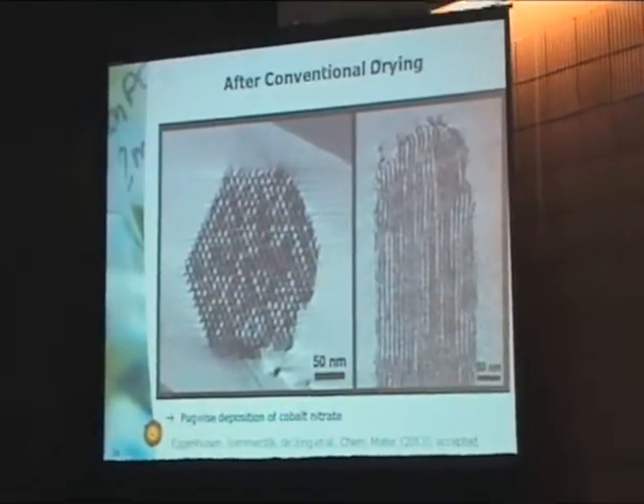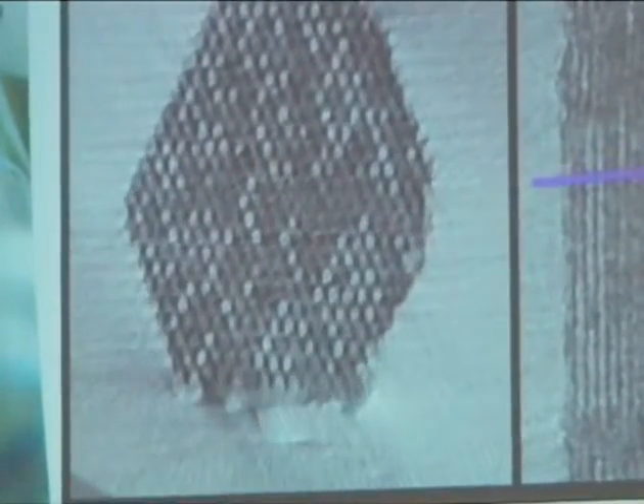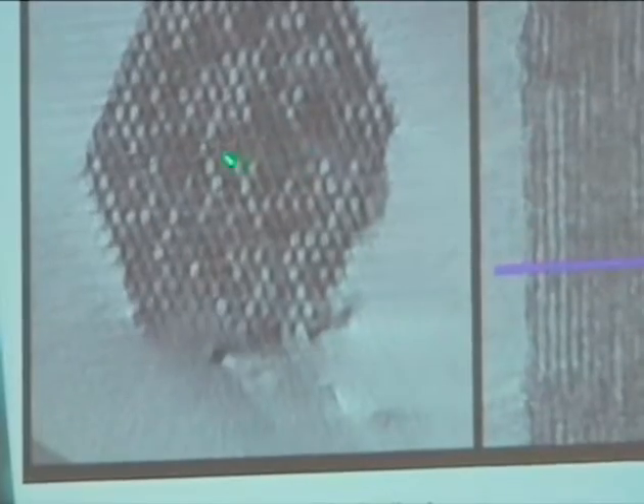So this is an SBA-15 particle, in this case with the electron beam parallel to the pores. In this case, the electron beam perpendicular to the pores, but this is from one and the same electron tomogram. So what we will do, and I will start the movie now, we will travel through this particle with the mesopores in this direction, and at every position of the bar we see an orthogonal cross cut from the electron tomogram in the SBA-15 particle. And what we clearly can see is that some bright spots are there, and the bright spots essentially are empty pores. But we also have uniform gray areas over a number of pores, and those are heavily loaded with cobalt nitrate.